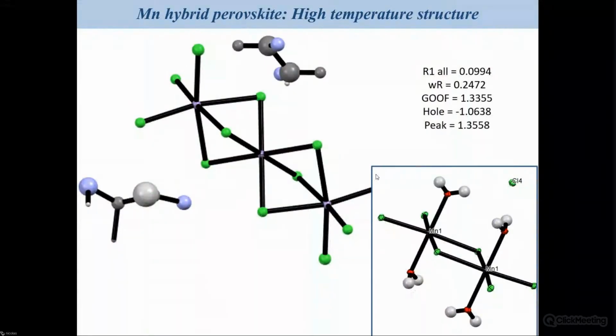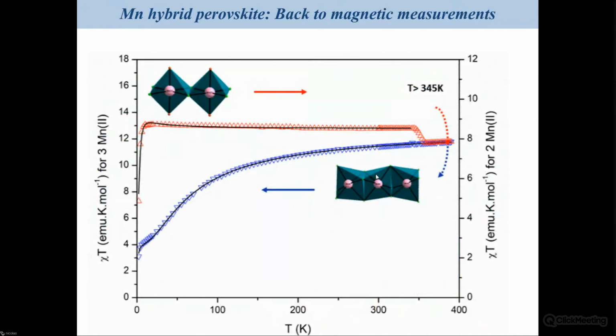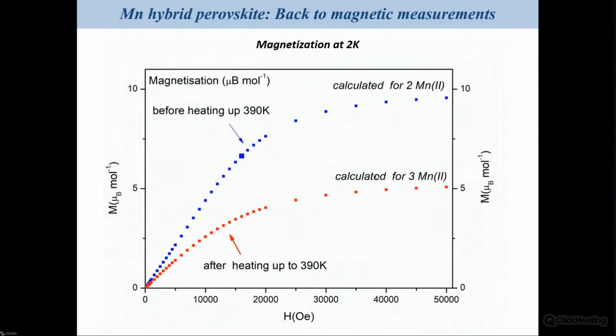So in that case, we have three different manganese interacting with only chlorine atoms. It was surprising, but the advantage of that high temperature structure is that it helped people studying magnetism to fit what happened after the first heating, which is completely in line with the measurements they made. So it means that it's probably the good structure, but of course you need to confirm that. And it helps you to fit the magnetization using three different manganese interactions.